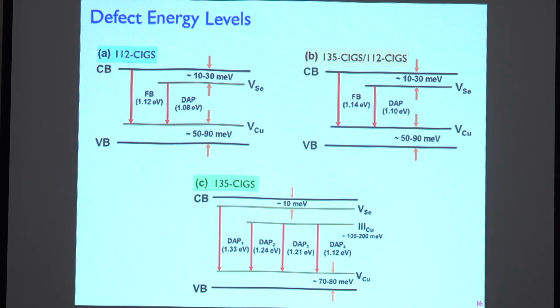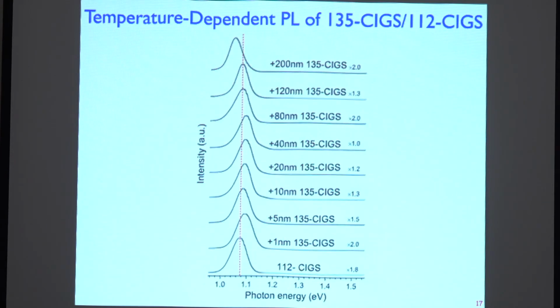And the thin layer of 135 on 112 is not much different, but for the 135 only, we have emission energies, 1 through 4, contributed by the deep level defect that is known as group 3 substitution on the copper site. So this is the case of only 135, and we do not observe this transition when we put some 135 on 112. And this is the temperature dependence for various thicknesses of 135 on 112. It starts as a blue shift for a very thin layer and shifts back to a red shift when we have a thicker layer of 135.